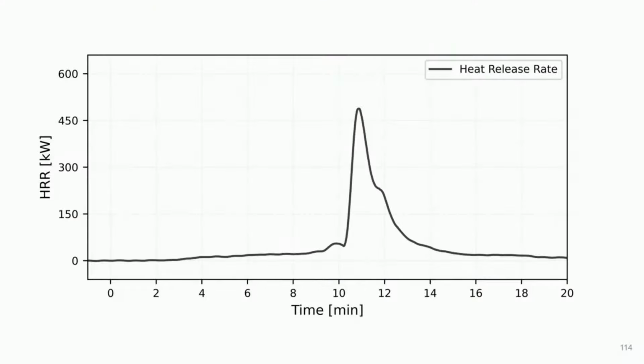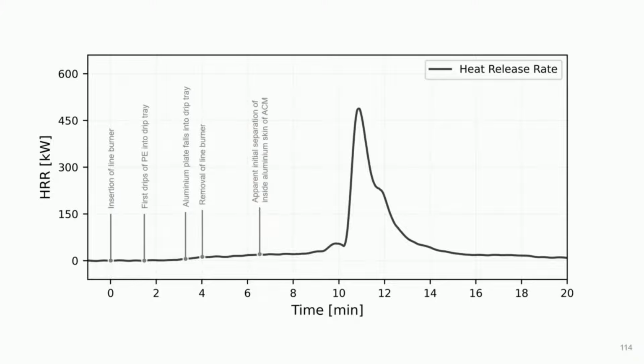So, just to return to the heat release curve that I showed before we viewed the video, this slide just recaps those observations. Insertion of the line burner at 0 minutes, first drips of PE at about 1.5 minutes. Aluminium plate on the top of the ACM PE shelf falls into the drip tray before the line burner is removed. The line burner is then removed after 4 minutes. The fire then grows gradually over a few minutes. There's some apparent partial separation near the base of the ACM as that fire is growing.